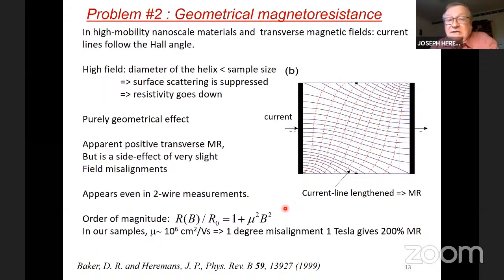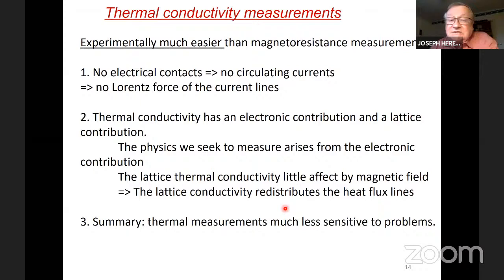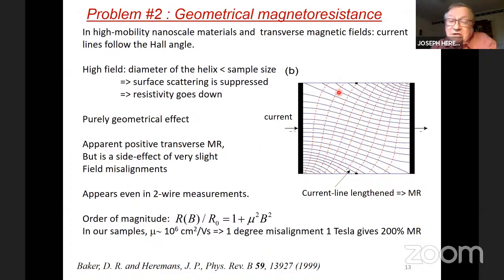The good news is, in thermal measurements, the situation is much less dire. First of all, we have no electrical contacts, so we have no circulating currents. There's no macroscopic Lorentz force or macroscopic current lines. Of course, there still is a Lorentz force on the carriers themselves. But the thermal conductivity also has both a lattice and an electronic contribution. And the lattice contribution, when it is large enough, say half of the measurement, that's good enough to redistribute the heat. In other words, the lattice contribution in a picture like this would be able to short circuit these current lines in the vertical direction and straighten them out again.